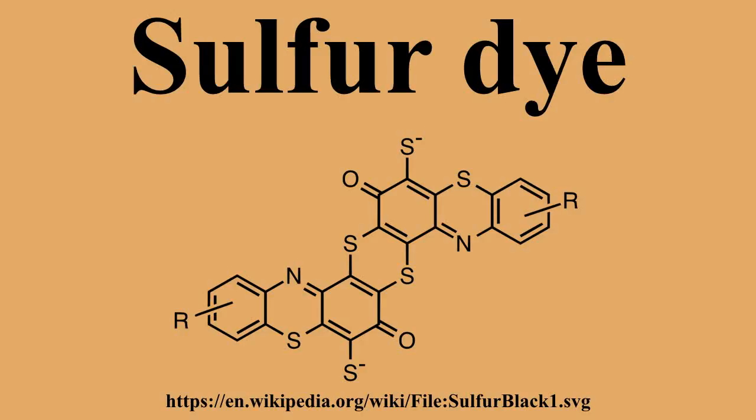It is accepted that the sulfide reduces the nitro groups to aniline derivatives, which are thought to form indophenol-containing intermediates that are further cross-linked by reaction with sulfur. The result is insoluble, high molecular weight species. Sulfur Black 1 is imperfectly understood, and the material is probably heterogeneous. It is speculated to be a polymer consisting of thianthrene and phenothiazine subunits.